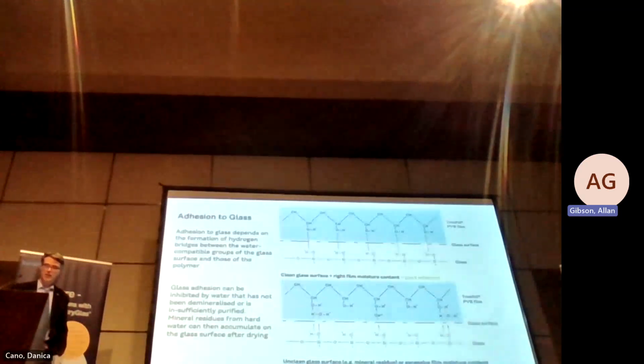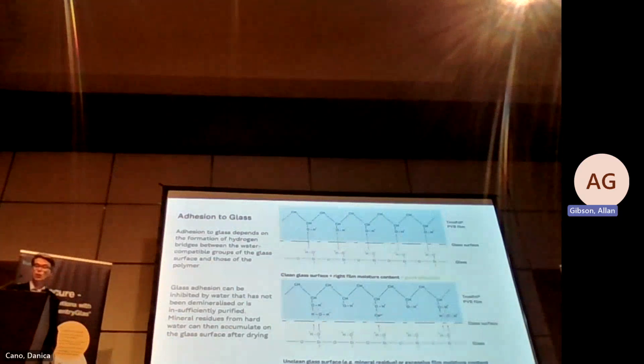Next slide, please. Proper glass cleaning requires quality water. Only demineralized water with a conductivity of less than 20 microsiemens is effective to ensure a strong adhesion bond of the polymer and the glass.